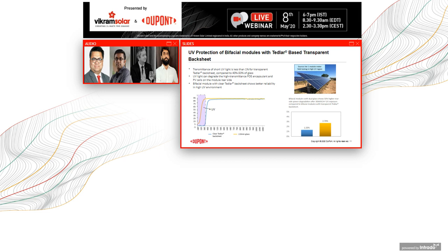Why is this the case? If we look at the transmittance of the UV of the clear backsheet versus the 2mm glass, we see here that shorter than 350 nanometers is the place where there's a lot of harmful UV that's present in the solar spectrum. And the clear transparent backsheet actually has a much lower transmission compared to glass, and this in turn can protect the rear side of the module from UV degradation, as well as degradation of the POE encapsulant that's there on the rear side.